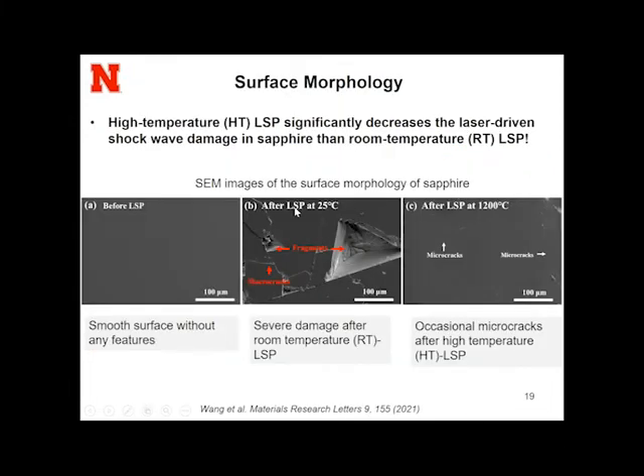So why we do sapphire is here. I show the reasons like this. In the beginning, we did the laser shock peening at room temperature. We found that even with optimization of the parameters, the laser shock peening at room temperature for the sapphire never works.